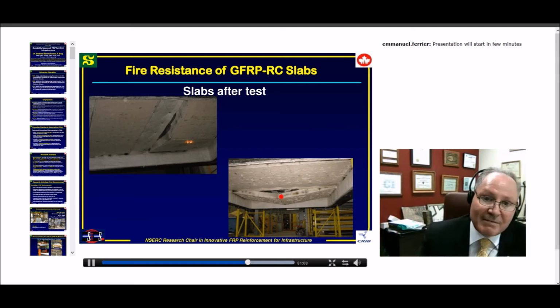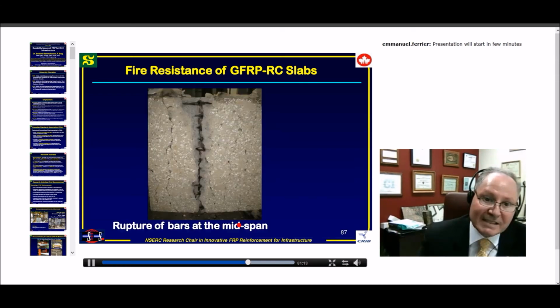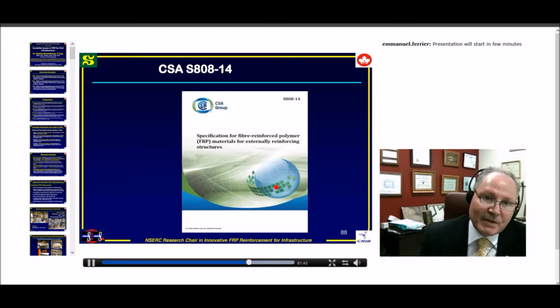So I can show you here some other results. This is the failure of the slab. As you can see here, it was really a tensile failure of the bars. This is in the middle of the span of the slab where it failed. You can see the bar. It was green, and now it's already black, as you can see, due to the fire. And it was by rupture of the bar. And it was about, as I told you, 3 hours and 10 minutes. So it was really extremely positive results, and hopefully we'll be repeating it for 40 millimeters.